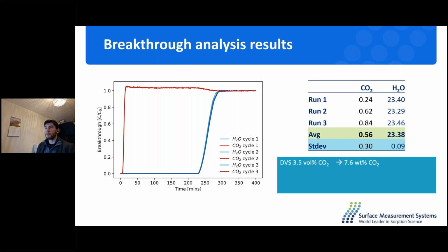So this is for the pure component, just CO2. If we were to look at the isotherm of water at 20% relative humidity, we would in theory get 24.4 weight% water. And if we put both of them together in the co-adsorption in the BTA, these results show that the amount of CO2 is diminished massively, while the amount of water stays pretty much about the same.